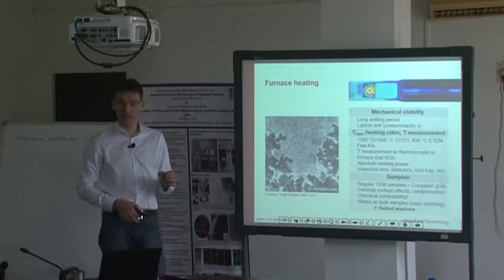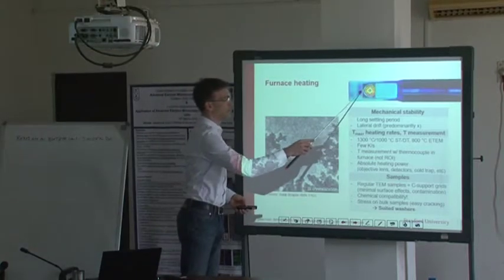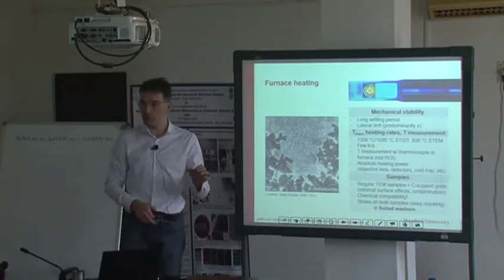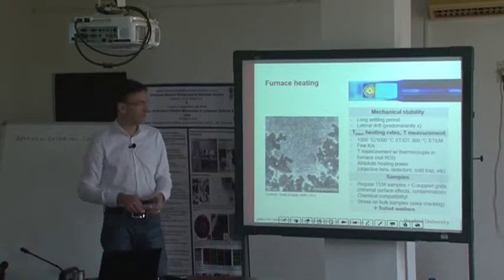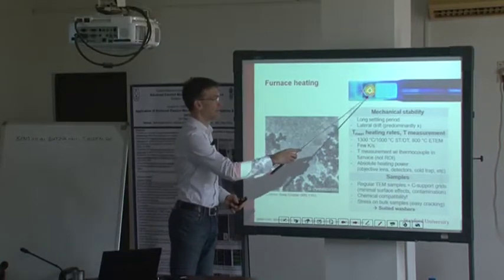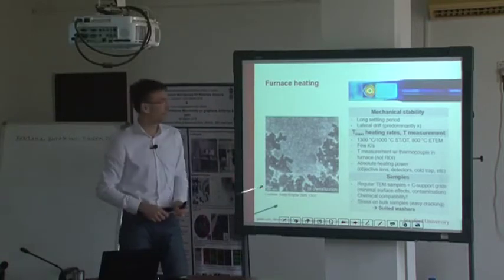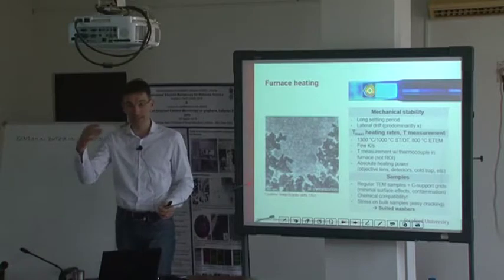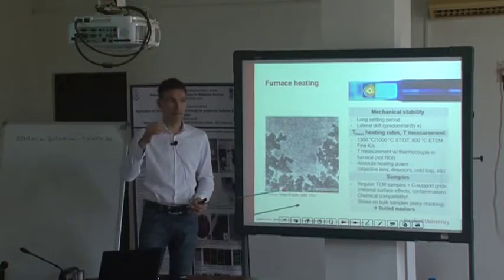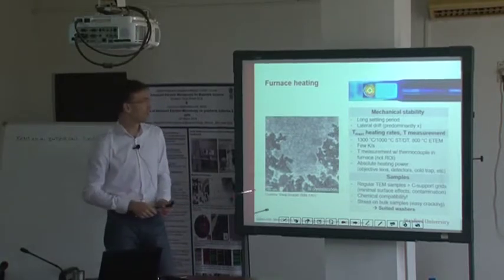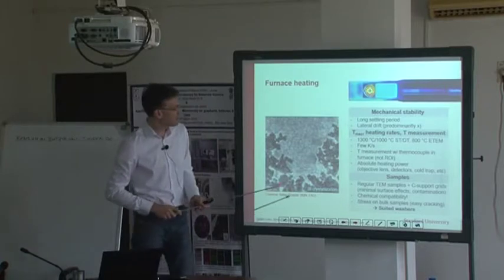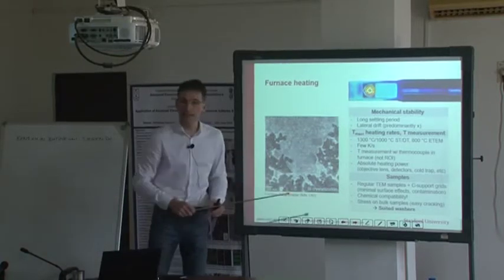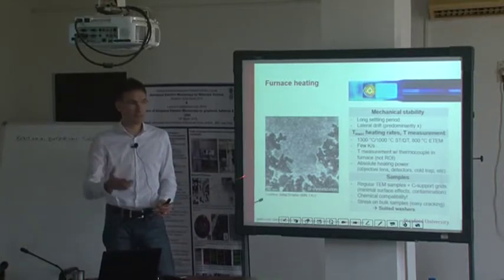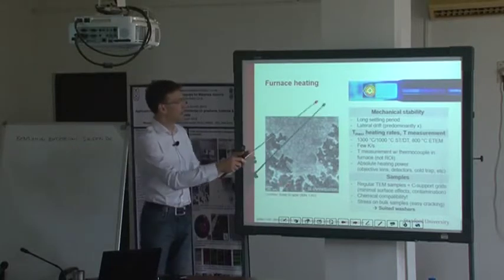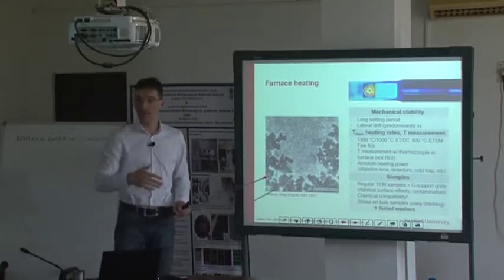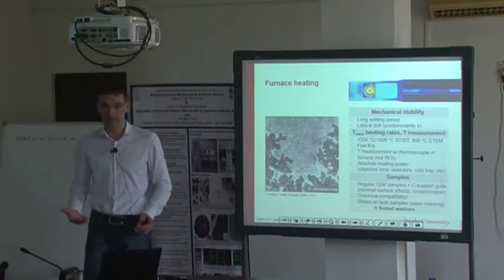One is the so-called furnace heater, where you heat the whole part where you mount your TEM sample. So you heat your sample from the outside. There's one big disadvantage here: the evolving heat loss at higher temperatures. If you want to conduct any chemical analysis with your EDS detector, you will run into trouble with infrared light on your EDS detector. So this is a big disadvantage: you cannot do chemical analysis at high temperatures. Another disadvantage is that you might end up with a strong drift of your sample, because whenever you heat, you introduce stresses, and drift might occur. People are interested in atomic resolution imaging, and with this you can hardly realize atomic resolution imaging.